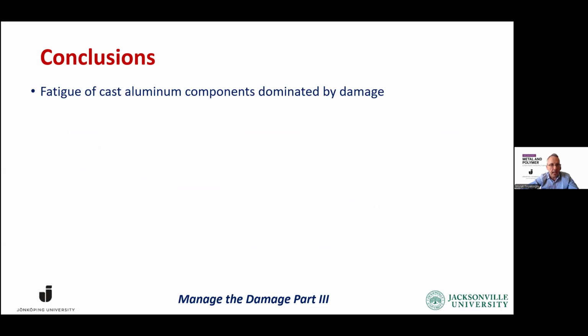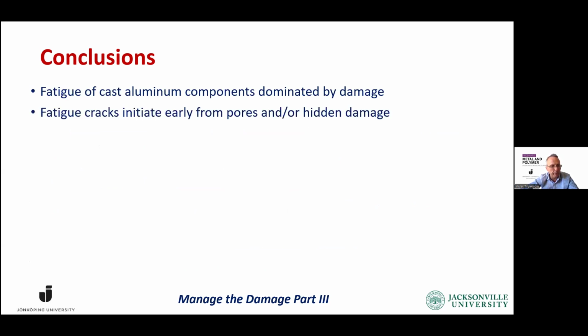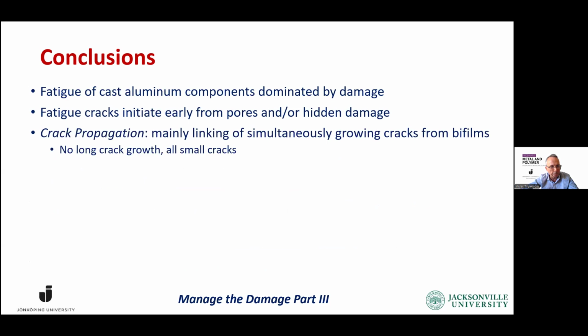The fatigue of cast aluminum components is dominated by damage. The cracks initiate early from pores or hidden damage. The crack propagation that we were taught in school does not apply in this case. It's mainly linking of simultaneously growing cracks from bifilms. There is no long crack growth. It's all small cracks.